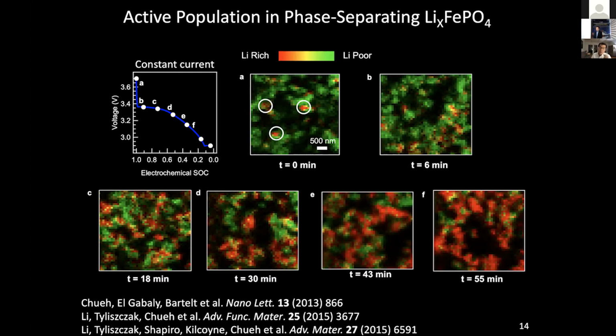And then you start putting lithium in by driving a current, but rather than receiving the lithium uniformly, you can see these hotspots that I circled out. This is actually where the lithium is actively inserting. If you go through these series of images very carefully, you will find that only a few % of the particles is actively receiving lithium at any given time. So the system is very far from being uniform.